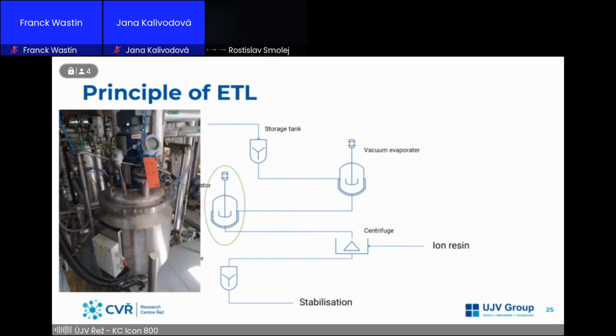And after that, you have the crystallizator. And now you can see the real difference between the volumes. The crystallizator is still beautiful, but it's a really small tank. It has around 130 liters volume. It's also double-shelled, continuously stirred. And in the outer shell, there's the cold water, which helps the oversaturated solution to start to crystallize. But it's really hard to get to that point without failing the process, because when it's oversaturated, you start a really fast cooling process, then it could really solidify up, and that's not really good for you and for my overtimes.